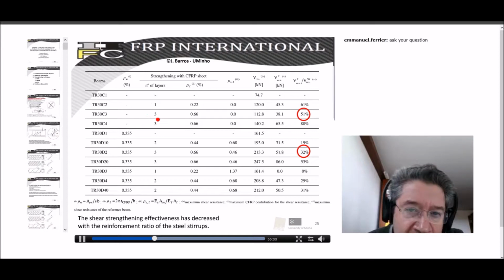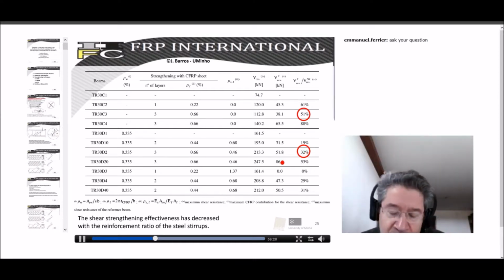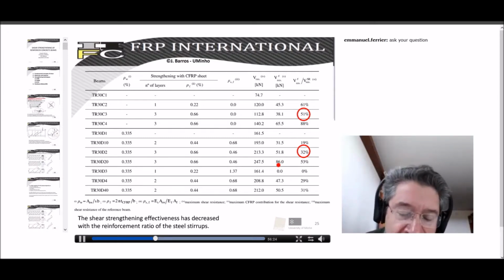And when we apply the 3 CFRP layers, we obtain an increase of the shear strength capacity for the beam. The increase was 51%. For the same beam, but with a certain percentage of 0.33% in terms of existing shear reinforcement ratio, assured by steel stirrups, we realized that the increase provided by the same shear strengthening arrangement was only 32%. This is observed in all experimental research carried out by several people: the shear strengthening effectiveness decreases with the increase of the reinforcement ratio assured by steel stirrups.